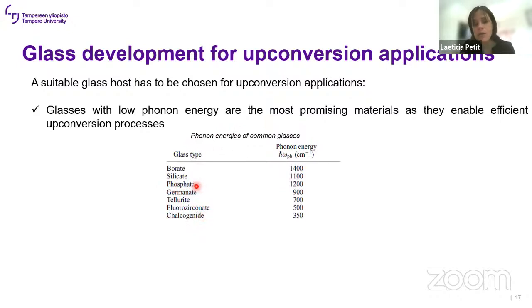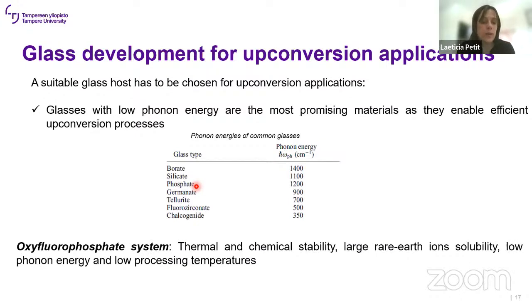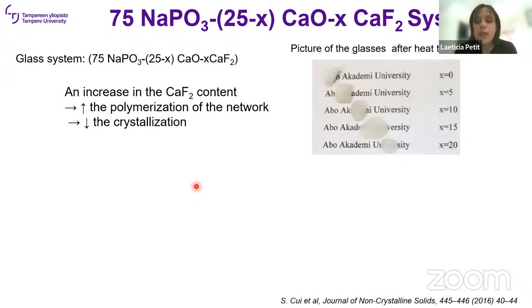And so, of course, the germanate, tellurite, fluoride, and chalcogenide are good glass candidates with low phonon energy. So we decided to work with this oxyfluorophosphate system because they have this good chemical stability, large rare earth ion solubility, low phonon energy, and low processing temperatures. So here's the composition that we have worked on since 2015-16. So it's a sodium phosphate with calcium oxide and calcium fluoride.